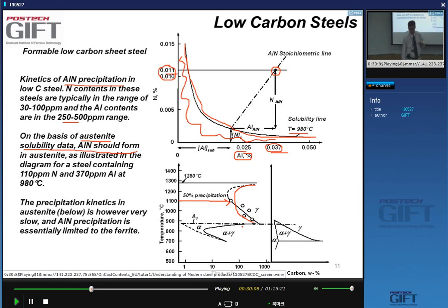the aluminum nitride. Now, we have to be careful, of course, because if we're looking at the real low-carbon steels, when you pass the transformation curve, you don't go from austenite to ferrite. You go through an intercritical region. So in that region, this is the precipitation curve. And of course, because it's a C curve, the rate of precipitation of the aluminum nitride is high at 800 degrees C, but at 700 degrees C and lower, it's again very slow.